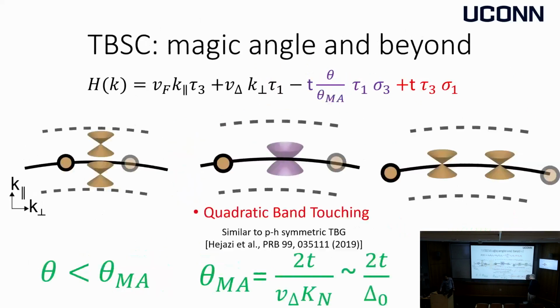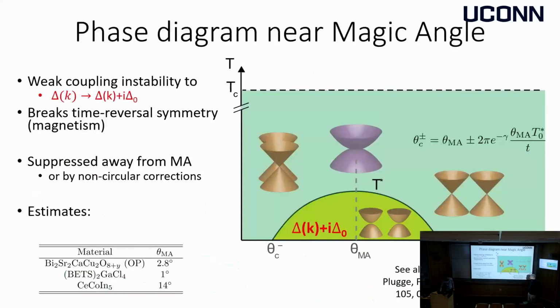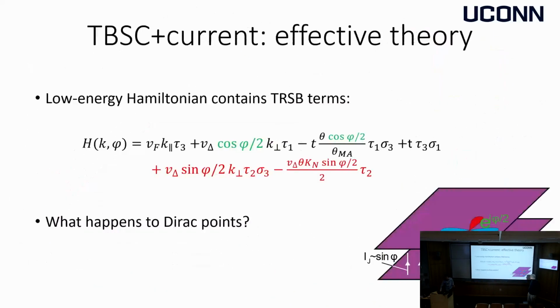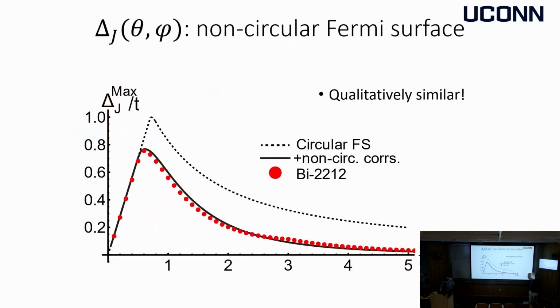Yeah. So actually, that's one of the points I've worried about a lot, specifically when doing this calculation, because if you rotate a circular Fermi surface, it still overlaps with itself perfectly. But if it's not circular, you start rotating, and it doesn't even cross. So I was really worried whether all these gaps and so on will go away, and they kind of do, but at large twist angles.